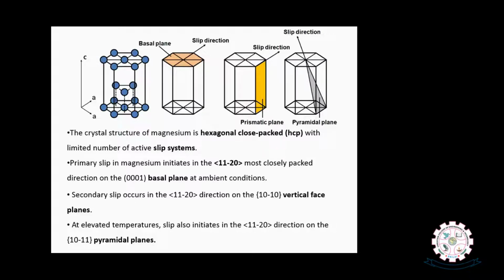The deformation of any material, particularly crystalline material, depends on the availability of a number of slip systems. In HCP crystal structures, in magnesium for example, primary slip is seen in the 1 bar 2 1 bar 0 close-packed direction with the basal plane, and secondary slip you can see in the same direction with prismatic planes, as schematically shown in this diagram. At elevated temperatures, slip also can be seen with the pyramidal planes. In order to activate slip with the prismatic planes and the pyramidal planes, we need to provide certain heat. We need to heat the magnesium alloys to certain temperatures where we can deform by activating slip in prismatic planes as well as in pyramidal planes.